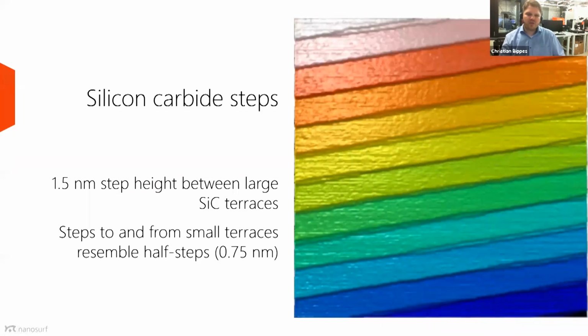Another example is a silicon carbide sample where you see steps, or layers of the silicon carbide, in terraces, and the distance between two of these layers or terraces is 1.5 nanometers. And sometimes you see also some smaller terraces here and here. These are half steps, and they are around 0.75 nanometers.